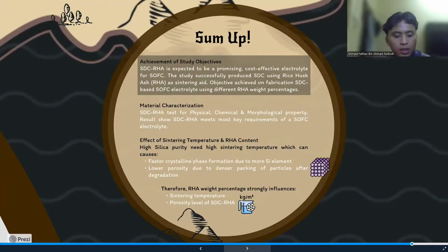In short, higher silica purity demands higher sintering temperature, leading to faster crystallization and dense packing, which reduce the porosity of the electrolyte itself. Analogically, RHA content is like a control knob. If you want lower temperature, you adjust the rice husk, and if you need a specific porosity of your electrolyte, you also need to tune the rice husk.